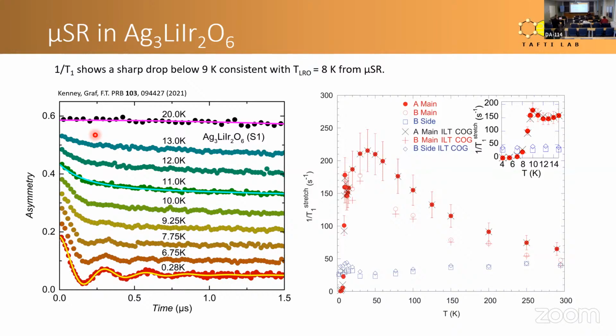But before they decay, if they are in a magnetic environment, they will perform Larmor precession in the local magnetic field. Then the decay products exit the material, and there are detectors covering the room where the sample is sitting. From the asymmetry in the detection of these outgoing particles, you can say something about magnetism in the material. If this asymmetry shows oscillations, you know that the muon was subjected to a local field. From the frequency of these oscillations, you can find the strength of the local field in the material.